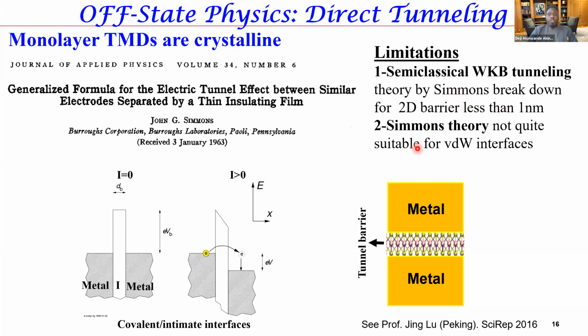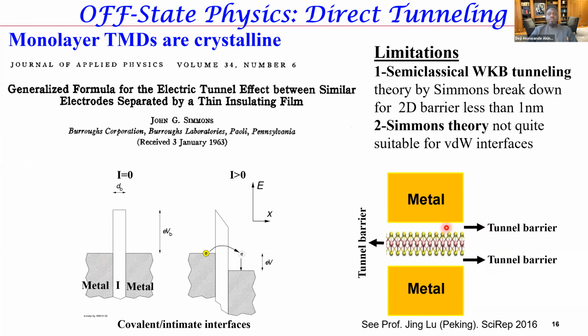And then the other reason, which John Simmons did not recognize, and you cannot fault him for this, was that this theory, in those days, they were dealing with epitaxial interfaces—intimate interfaces between the insulating barrier and metal. In the case of the 2D material, this is not the right picture. The actual picture is you indeed have a van der Waals gap between the material and the metal, so it's not an epitaxial interface.